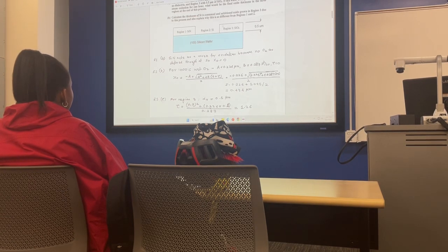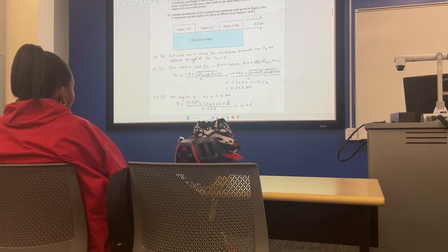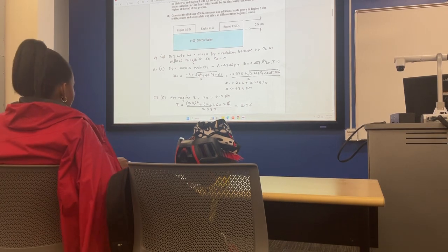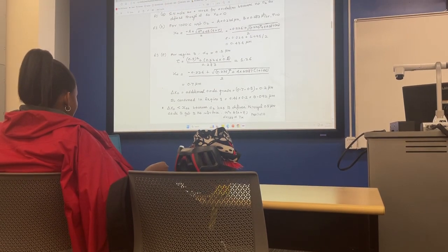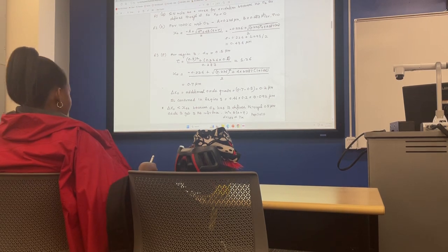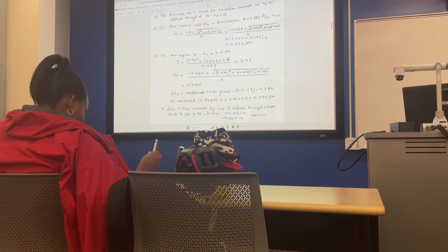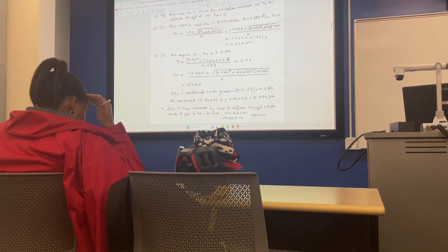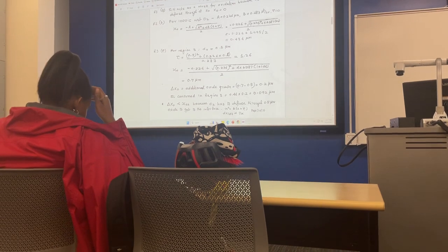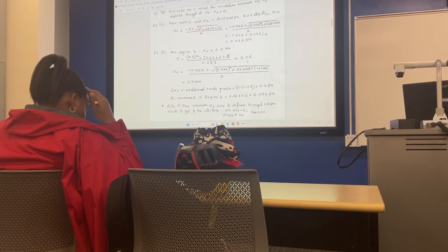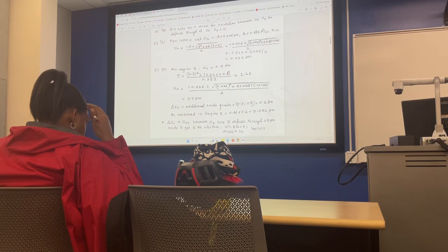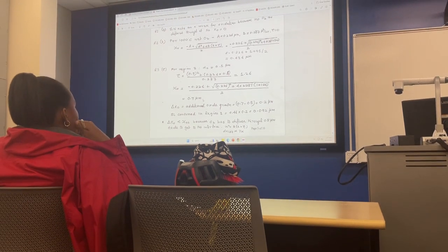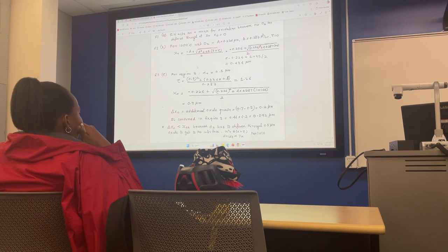Then up here, you have an oxide present. So when you do the oxidation, you have to find the tau based on this half a micron thick oxide, and most of you got that right. So first you get the tau corresponding to half a micron thickness, which is d squared plus A d divided by B. That's how you calculate the tau to take care of the initial thickness, and that gives you tau of 1.26 hours. And now you just use the standard equation here, with t plus tau, and this gives you 0.7 micron. So this is what it is in A, B, and C.